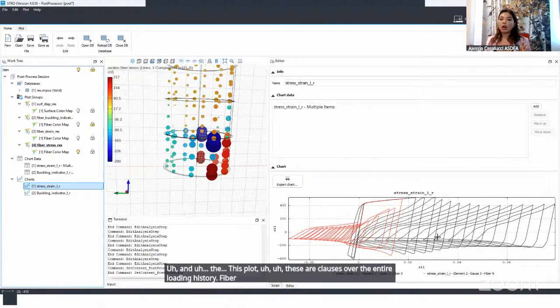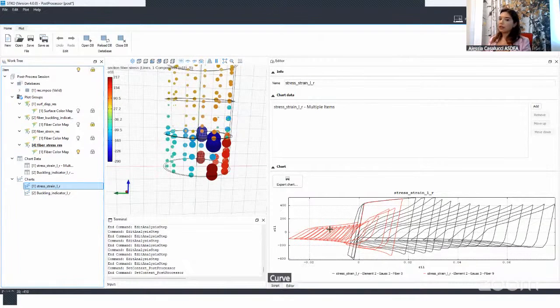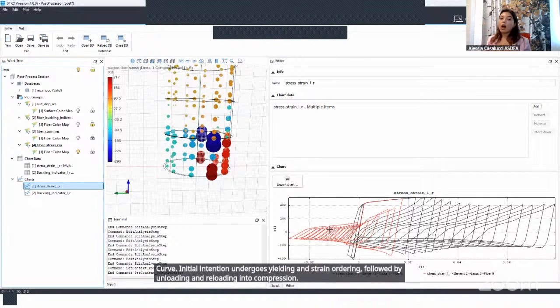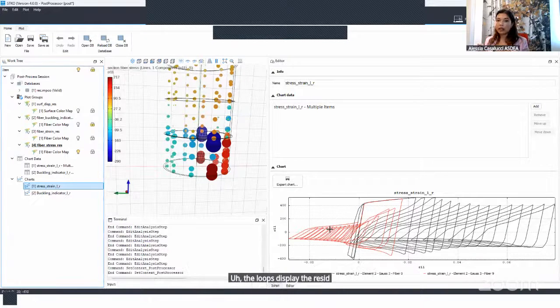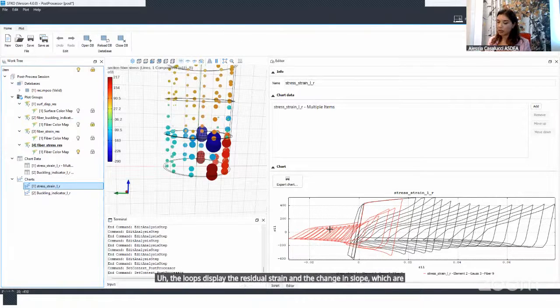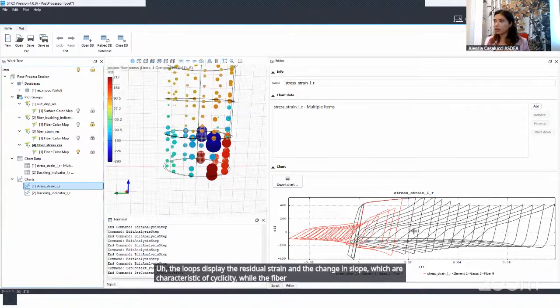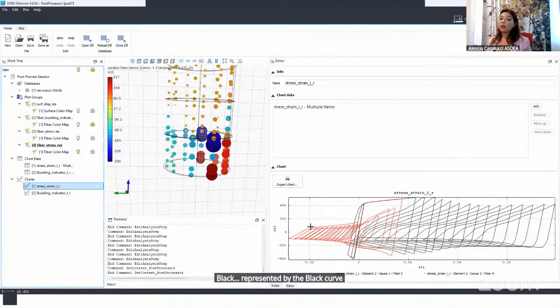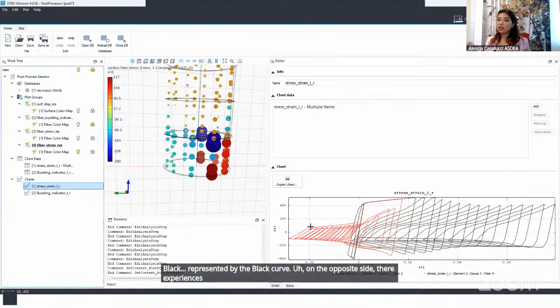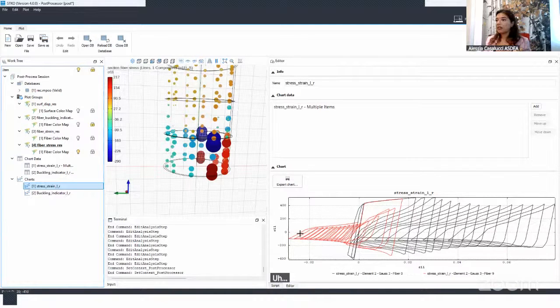Fiber 9, the red curve, initially in tension, undergoes yielding and strain hardening, followed by unloading and reloading into compression. The loops display the residual strain and a change in slope, which are characteristic of cyclic plasticity, while fiber 0, represented by the black curve, on the opposite side, experiences large compressive strains. Its hysteresis loop indicates localized buckling under repeated compression. Both fibers exhibit strain values that reach almost 0.04, confirming that they undergo significant plastic deformation.